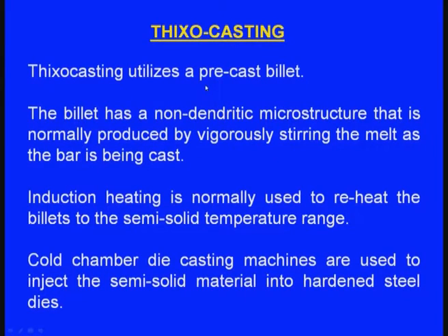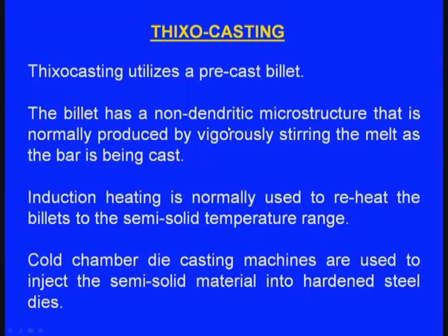Thixo casting utilizes a pre-cast billet. We have to buy this billet in the market and it is pre-cast under certain controlled conditions, under a controlled environment. The billet has a non-dendritic microstructure. You see this? This is very important. It has a non-dendritic microstructure that is normally produced by vigorously stirring the melt as the bar is being cast. As we are getting this bar, it is vigorously stirred.